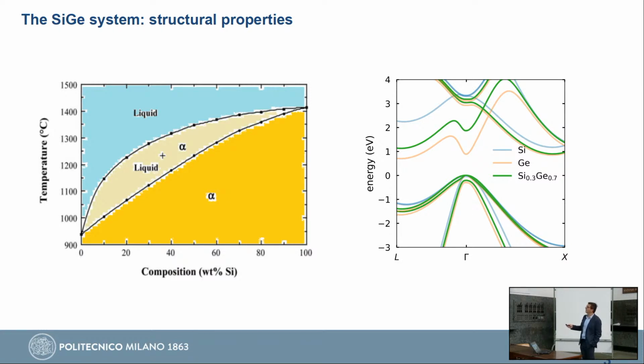So we have pure silicon on this side and germanium on the other side. This large yellow area means that any composition of silicon and germanium will give me a perfect crystal, an alloy with perfect miscibility. So I will form whatever combination of silicon and germanium, and the band structure will evolve accordingly. Here, in a bit transparent, you see the original band structure of silicon and germanium. If you mix them up, you see that you have a continuous variation between one and the other. So you can have a very gradual variation of properties changing the composition.